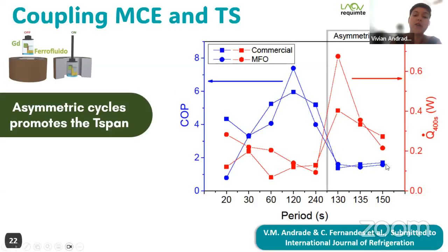The COP values at the asymmetric cycles did not increase. What we could increase was the cooling capacity. After 400 seconds of operation, we achieved higher cooling capacity for our small device operating asymmetric cycles. So of course, if we take a long time, asymmetric cycles achieve lower temperature spans, and this is why we have higher cooling power. But the COP takes into consideration the whole cycle, and we didn't gain in the asymmetric cycles.